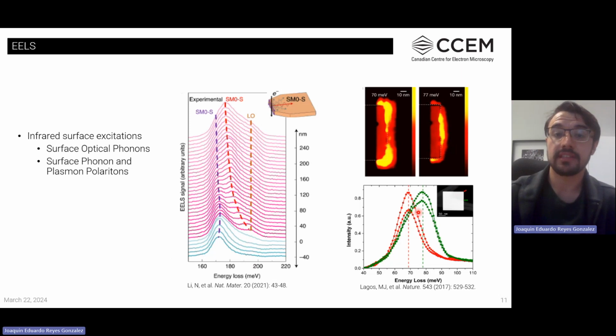In the bottom, you can see the EELS spectra associated with the edge, here in green, and the corner, here in red, by locating the probe and rastering for a period of time in that particular region. You can see two spectra. This is because the experiment consisted of locating the probe farther away from the sample to explore how the coupling of these surface phonons with the electron changes as a function of the position of the beam.